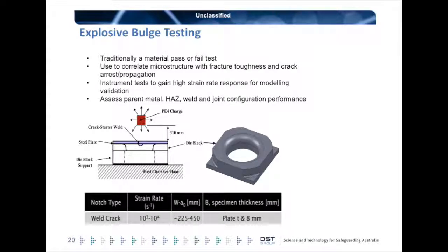And typically, we test a range of temperatures, and what we're looking for there is the ductile brittle transition temperature of that steel plate. The more energy you can absorb at a lower temperature basically means that that material is much tougher in terms of its fracture toughness. And ideally that's the sort of steel you want in this situation when you're getting explosive loading